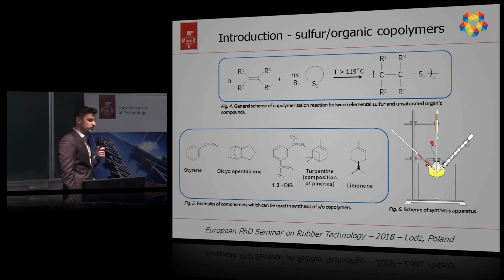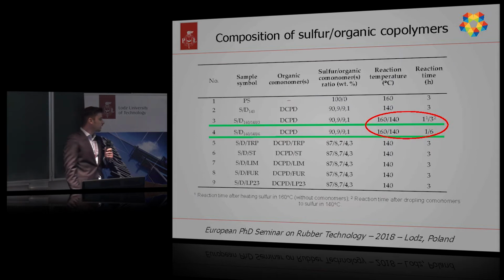And in my research, I used a classic glass four-neck reactor, which was equipped with condenser, mechanical stirrer, thermometer with thermocouple to synthesize sulfur organic copolymers. I synthesized one polymeric sulfur and 8 various sulfur organic copolymers, 3 of them based only on sulfur and dicyclopentadiene, but 5 of them based also on another comonomer, which was turpentine, styrene, limonene, furfural, and LP23. And LP23 is a liquid thiocol rubber.